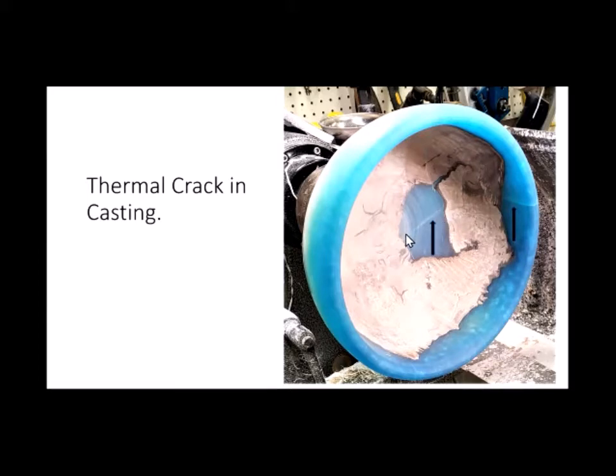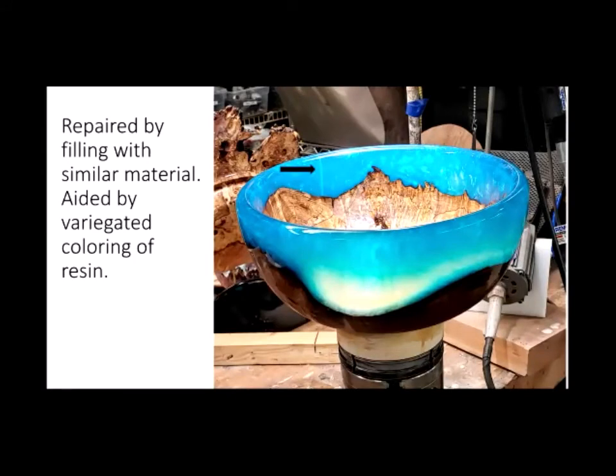And it was a thermal crack. Again, it had gotten too hot, and as it cooled, the plastic shrank. And fortunately, it was just one crack. And so I filled it with a resin that didn't quite match. And you can see it right there on the finished product where it was.